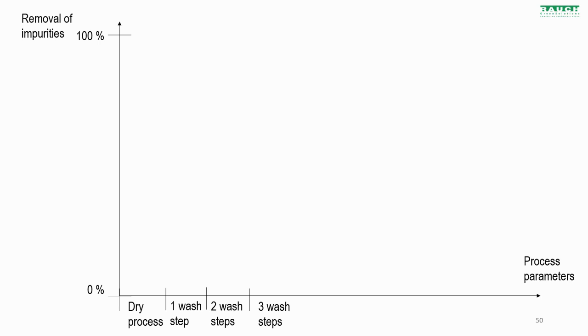There could be two, there could be three. What I showed you was that there were 3 wash steps: pre-wash, hot wash, cold wash. Inside the wash process, you can choose parameters. Water temperature. In the hot wash process, you can go higher up to have better results. It's like your washing machine at home.